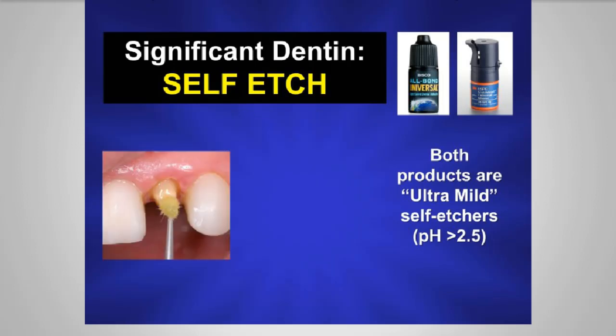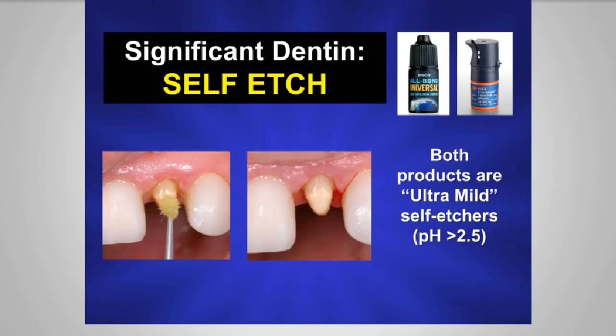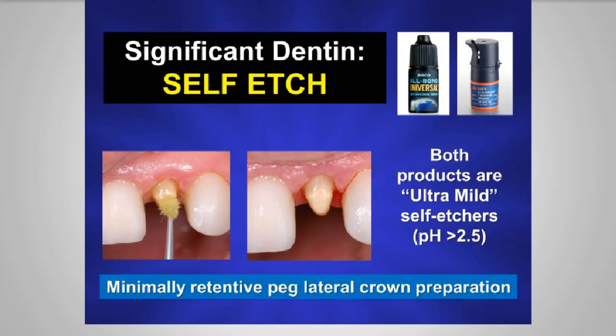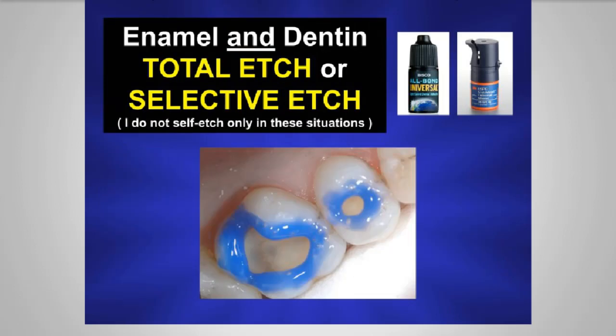And what about when you have both dentin and enamel? Say we're going to do a class 1 or a class 2 direct composite restoration. Well, that's up to you. I would not use these in a self-etching mode. In that case, I would either use a total etch or a selective etch, where just the enamel is etched, then it's washed off, and you go ahead and place your restoration using that type of protocol.